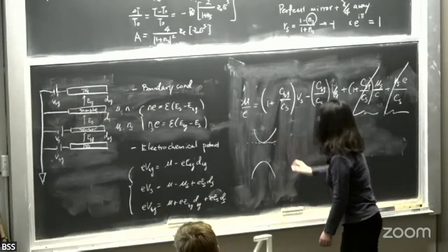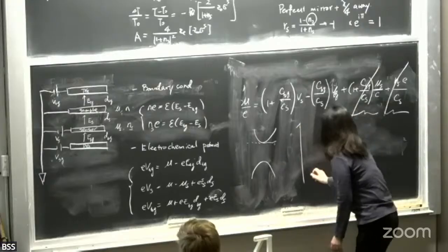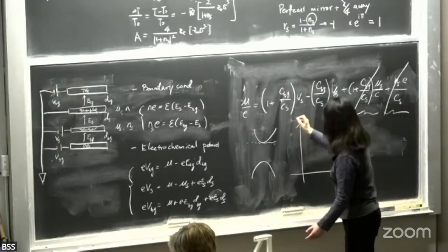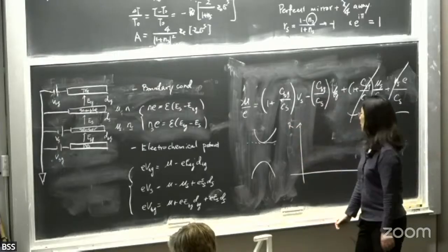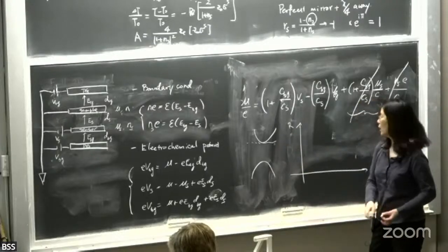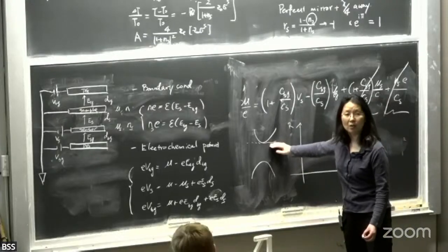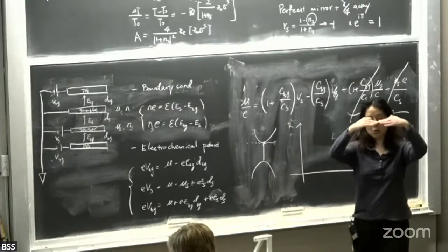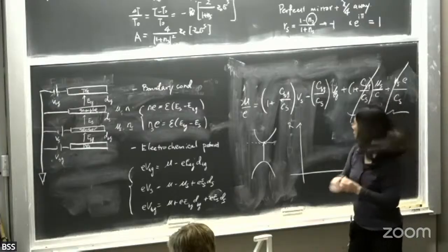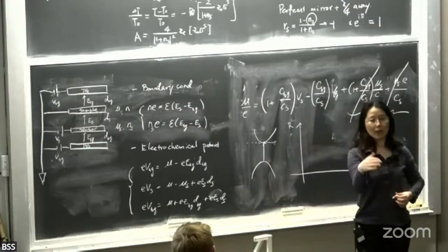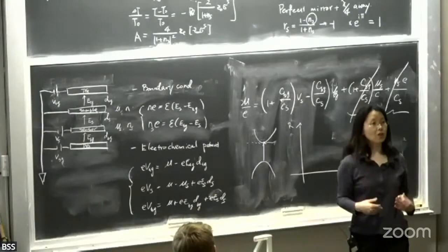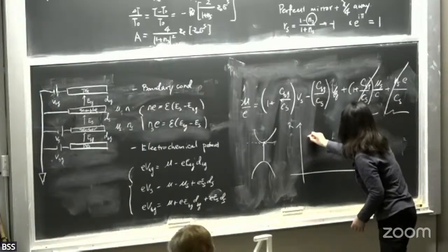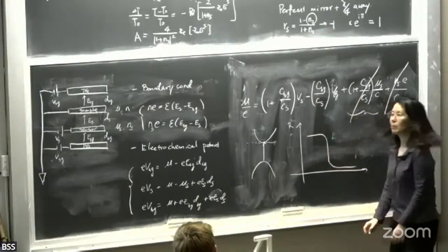Then in this case, if we look at reflection or transmission, in this case reflection, it's very sensitive to where that chemical potential is. So if the chemical potential is a little bit above this, then this transition can be blocked. And if it's below, you have a large transition. So the signal can go something like this.